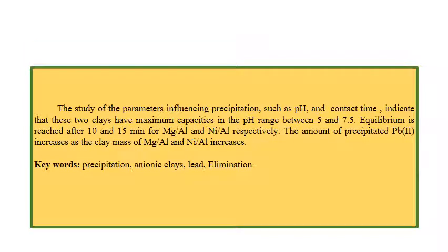The study of the parameters influencing precipitation, such as pH and contact time, indicates that these two clays have maximum capacities in the pH range between 5 and 7.5.